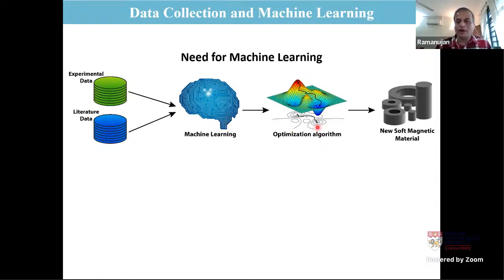And then we have an optimization algorithm. Why we need an optimization algorithm is because, as I said, we want to optimize the properties. Depending on the specific application, the weightage you give to different properties can be different. For example, if it's an iron cobalt alloy for high temperature aerospace applications, for all electric aircraft, which a lot of people are interested in, then you need high TC, because you want to operate it at those higher temperatures. But if it's a room temperature application, you would give less weightage to the Curie temperature. So depending on your specific application, one needs to use an optimization algorithm to produce the right composition, which will give you the properties of your interest.